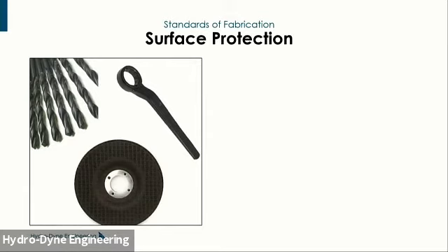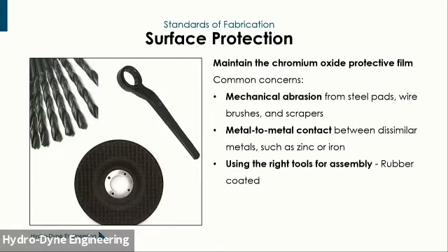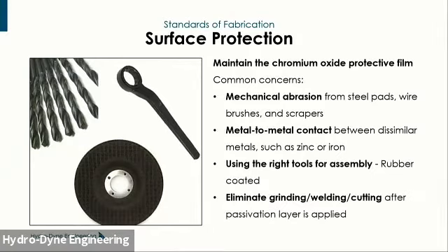So we've taken all that time to pickle and passivate the steel and dry it. So then when we fabricate further, we want to make sure that we protect that passivation layer. So that means we don't want metal-to-metal contact with dissimilar metals. We really don't want to be scraping or brushing on the steel to interfere with the passivated layer. And we have to use the right tools for assembly. So if we have to hammer on the steel, we would use something like a rubber-coated hammer. And ultimately, we really want to eliminate grinding, welding, cutting after the passivation layer is applied. If the wrong tool is just laying on the surface, that can damage the passivation layer and show up as a rust stain later. So we really have to take the time to fabricate correctly so that that doesn't happen.